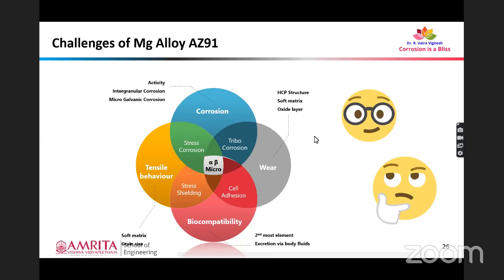For example, if these phases are present in a completely dispersed manner, then we'll have good corrosion resistance. But in case this beta phase is precipitated as a continuous network, we'll end up with a high corrosion rate and intergranular corrosion too. Why? Because the alpha phase is more anodic than the beta phase.